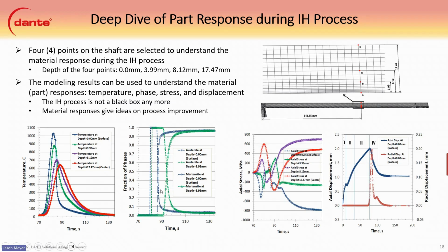So we can see the fraction of phases that are occurring. And then this all leads to some important stuff, the stress reversals in the part. So we can see the axial stress here. We're starting with the blue, which is the surface measurement. You can see that it goes quickly to compression here from the heating, and then it works its way up. And then once it starts to transform to martensite, it has another drop down to compression. And then through these phase transformations, it finally ends up at a higher compression here.